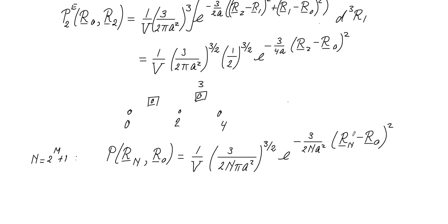We find that for a Gaussian chain, I always have a Gaussian distribution for the end-to-end distance. That's the same as for a freely jointed chain. Also there we found a Gaussian distribution with an n in the denominator. So when we see only the distribution of the end-to-end distances of two chains, it's impossible to tell what the details of the interactions are. In the end, all the chains will behave as Gaussian chains, and they will all have an end-to-end distance distribution like this.